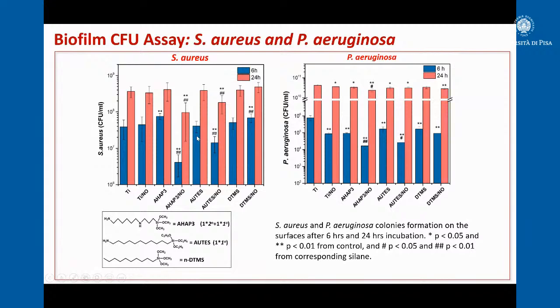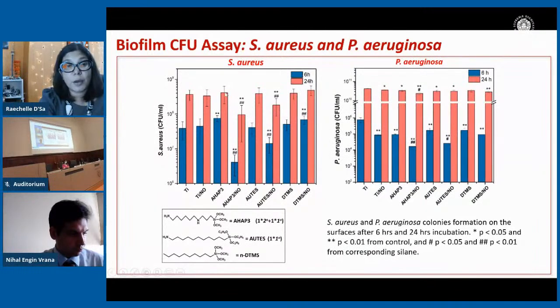And we see that the AUTES surface has a 0.8 log reduction in the amount of bacteria after we tether nitric oxide onto the surface at 6 hours. Now, after 24 hours, even though the number of bacteria grow, the same trend holds. We see a 1.5 log reduction here for the AHAP surface and a 0.8 log reduction here for the AUTES surface. And just to remind you, the AHAP surface, which shows the better bacterial response, has the 2 amines that are capable of binding nitric oxide. The AUTES surface has the 1 amino group capable. So this should be able to hold a bit more of the nitric oxide onto the surface.